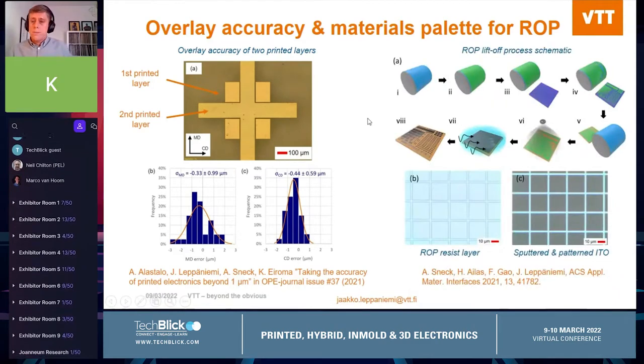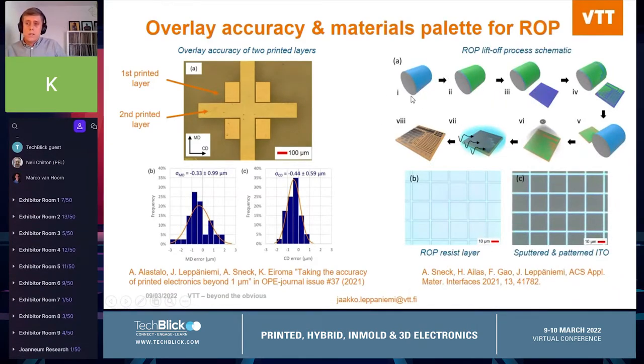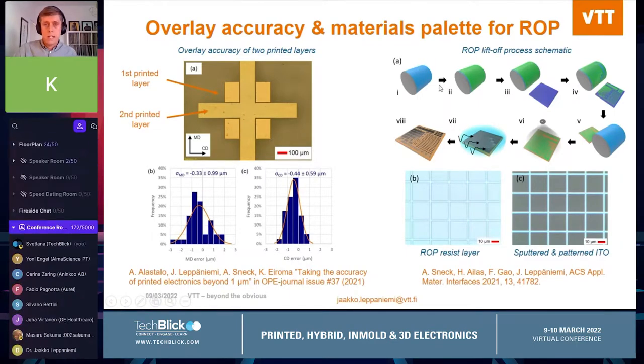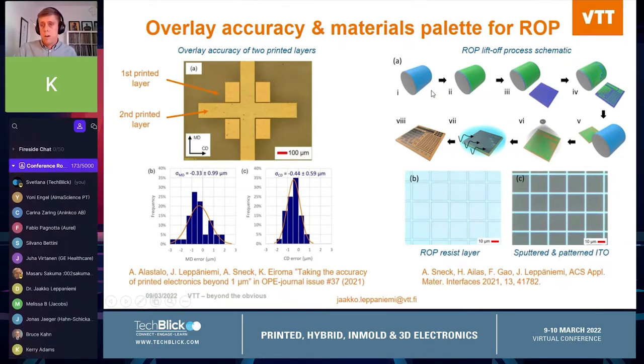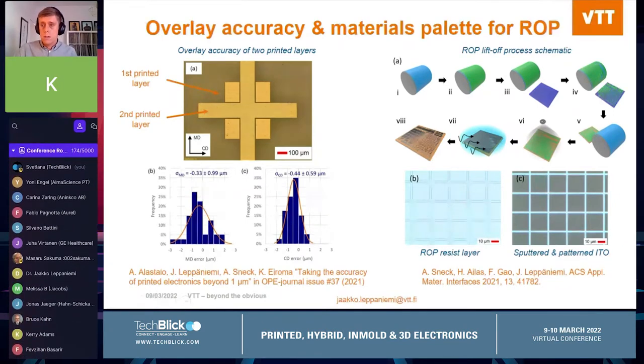As a second aspect, the ROP can also be used as a resist printing method to enable a very wide materials palette. Conventionally, nanoparticle inks, polymers, and metal oxide precursors have been printed with ROP. However, this material selection is still limited for ROP and in general in printed electronics. For example, low work function metals like aluminum or metal oxides like ITO are hard to print as inks. This material palette can be expanded by VTT's ROP-based lift-off patterning process.